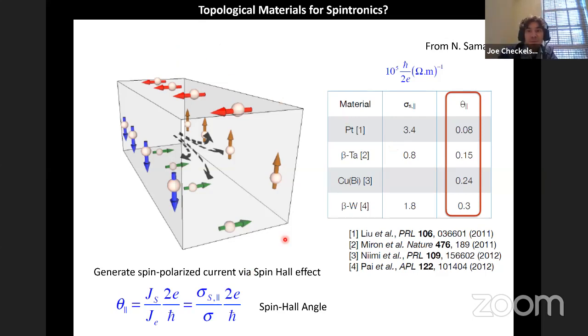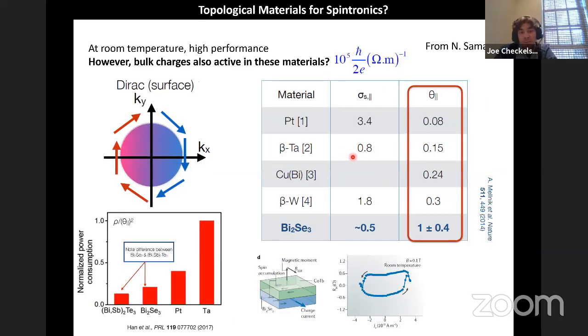And in terms of their performance, there's different ways of characterizing them. One way is the so-called spin Hall angle. And the amazing realization a few years ago was these very conventional topological insulators like bismuth selenide appear to have a huge performance, a very large spin Hall angle, which I think is not particularly well understood, but is certainly appreciated and recognized in this subfield. So it could be that this concept might have very deep roots, and this broad array of topological materials could even be another way of bringing these materials to bear. It's just something I didn't have time to really touch on, but I wanted to advertise.